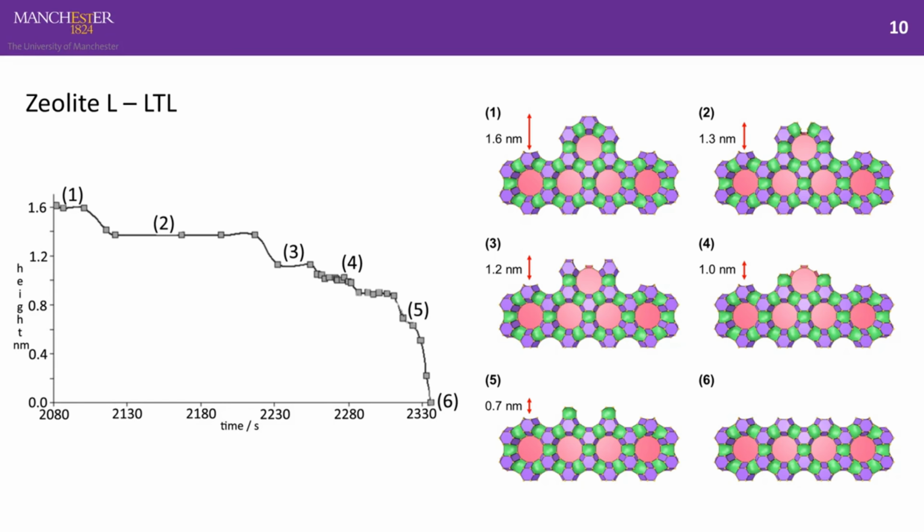So those closed cages are all units where each corner, or tetrahedral atom, because this is a zeolite framework, is connected to 3 other tetrahedral units. So that's called Q3, and that's what defines a closed cage. So a cube, for example, is a Q3 cage, because all corners on a cube are connected to 3 other corners. So that suggested that closed cages are rate-determining steps during crystal dissolution, and that they are metastable. So they should be rate-determining steps during the crystal growth as well. So they make a good candidate for a general building scheme for these types of crystals.